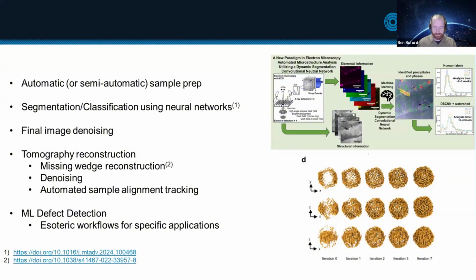When you're doing a tomography measurement, you can't measure directly in plane of the sample. You get too much absorption through the rest of the sample. So you're missing that information. But through an iterative approach, you can reconstruct without that, and then use that end result to predict what that data would have been and run it through the same reconstruction algorithm. And machine learning trained on that, you can train on one kind of generic data set and then use it on many other data sets, and it works pretty well.